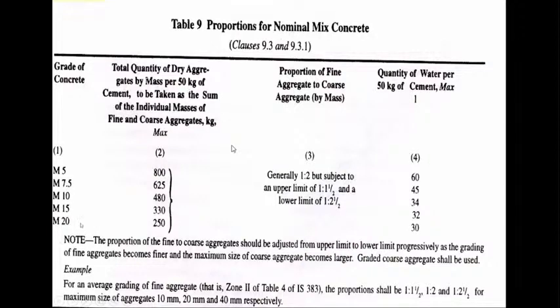So if you take M20, for 50 kg of cement, you will use 250 kg of fine and coarse aggregate put together. Mind you, it is total aggregate. And mind you, it is dry aggregate. The aggregate has to be absolutely dry.